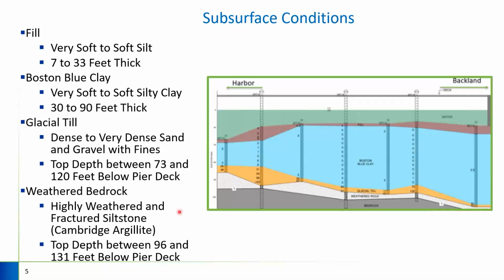And then finally, your weathered bedrock that consisted of highly weathered fractured siltstone. The image on the right shows both weathered rock and bedrock. This is a preliminary figure. Once we did a detailed evaluation of the rock cores and did some unconfined compressive strength testing, we determined that this was more of a weathered rock layer that was coreable, and so we redefined that in our final report as weathered rock. This was encountered anywhere from about 100 to 130 feet below the pier deck.